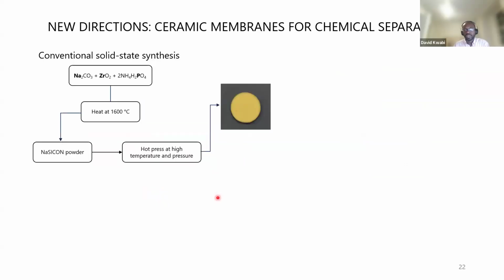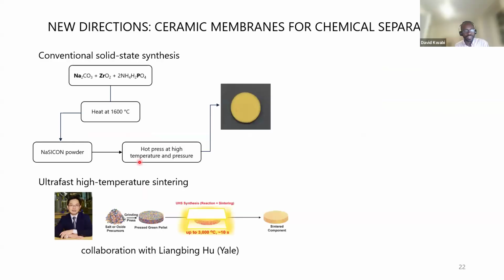And then lastly, I wanted to mention one more area in terms of new directions for the group. We're hoping to go away from this conventional solid state synthesis where we have to heat materials to extremely high temperatures for extremely long times, and develop new ways of fabricating these ceramic membranes, such as NaSICON and others, for a variety of different applications. One fabrication technique we've been very excited about was developed by my colleague at Yale, Liangbing Hu, where you take your precursor powder and press it into a pellet, and he's developed an ultra-fast high-temperature sintering process that does go up to high temperature, but only for less than 20 seconds, in the order of 10 seconds or so, before you actually get your final membrane.